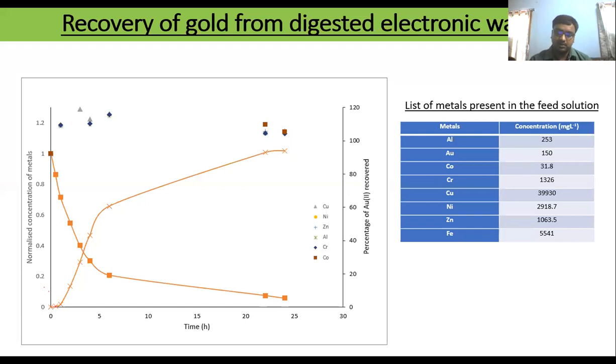We didn't have that facility in our lab, but it has been done by some other lab, that if we can remove this iron from here, we can get a faster recovery of gold. So you can see from this, it will not take 25 hours to extract all this gold, because if we can eliminate the interference of iron, we can get all the extraction within 10 hours, and then you can do the recovery faster as well. So from this result, you can see we got more than 90% recovery of gold, which is very good, of course. Now this membrane, we used it for a long time.